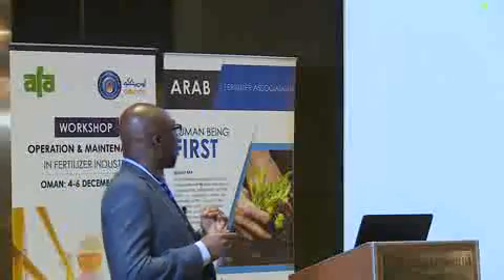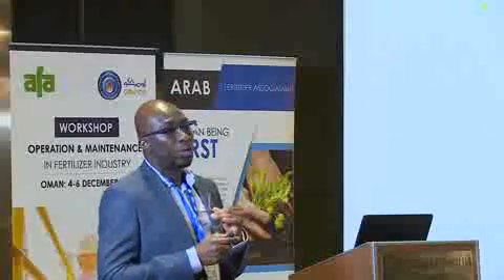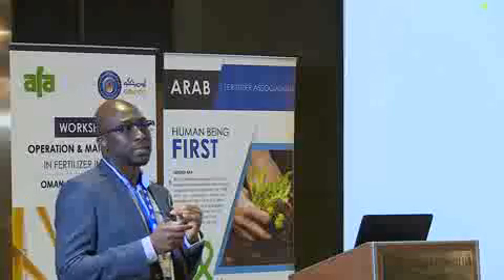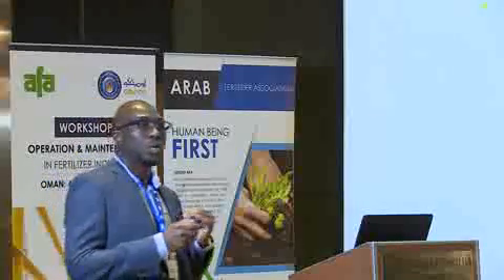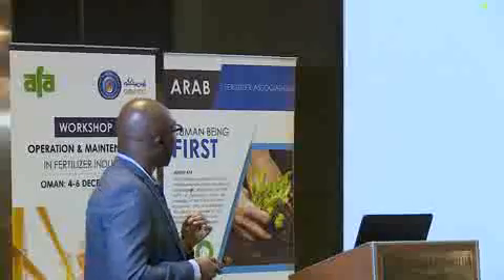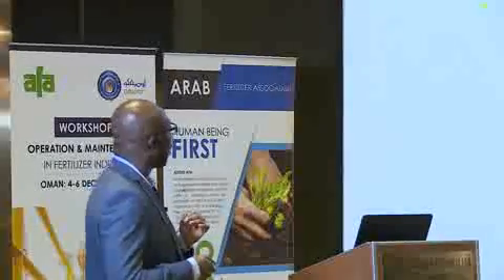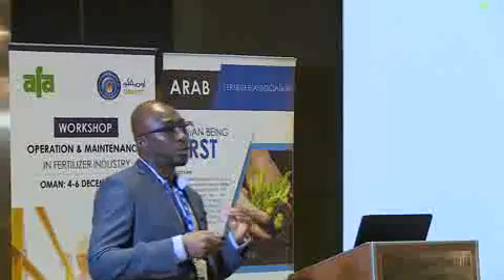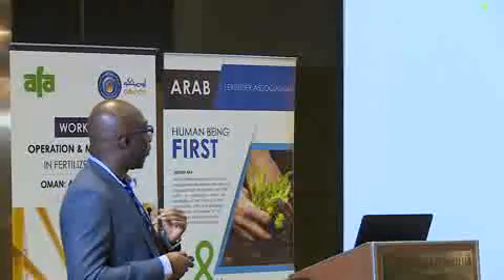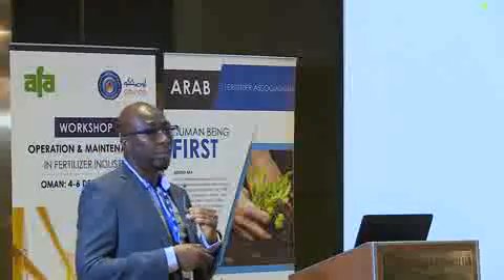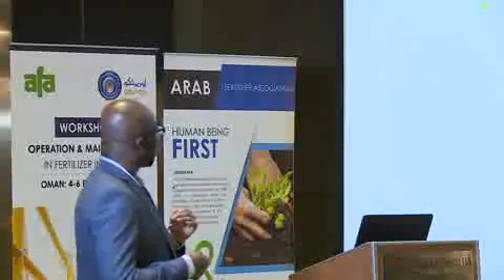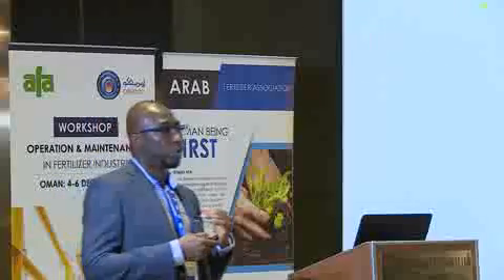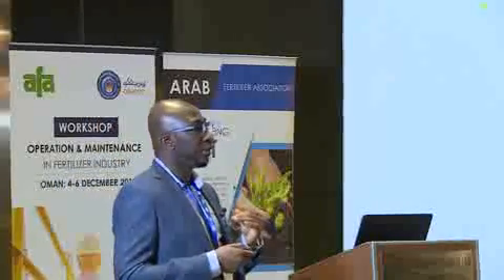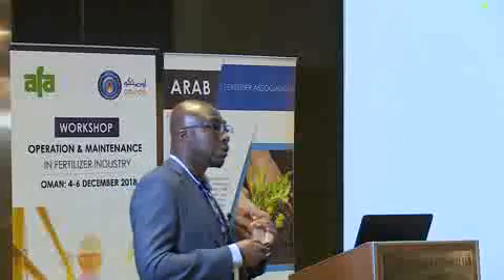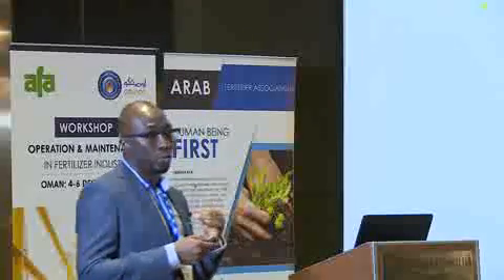But because we license plants in different parts of the world, when we have clients who are in colder climates, they ask us, hey, now you are selling us a duplex material. What about minimum design metal temperatures? And this became an issue because for large parts made from large forging blocks of Safurex, then meeting impact values that the clients were specifying became an issue. So to be able to solve this, we sat down and thought, well, this material Safurex that we have has really good corrosion resistance. How can we improve the mechanical properties at sub-zero temperatures without impacting on the corrosion resistance?